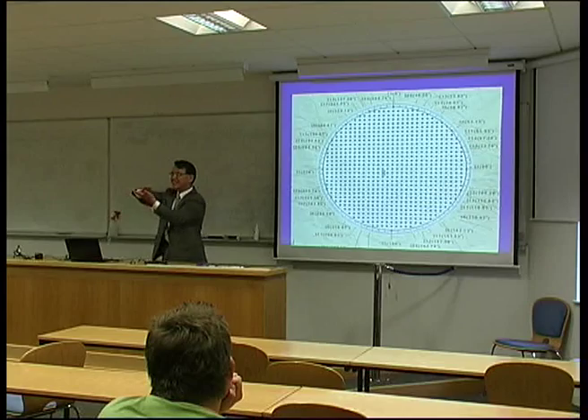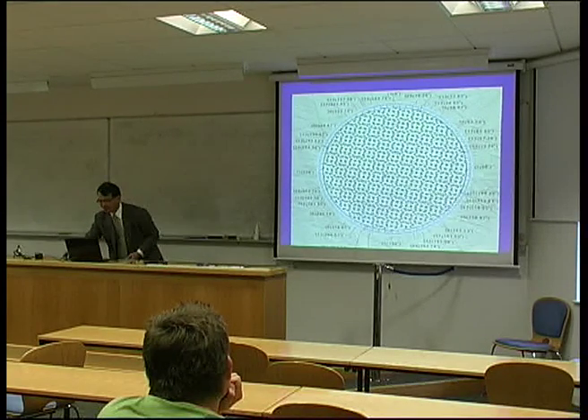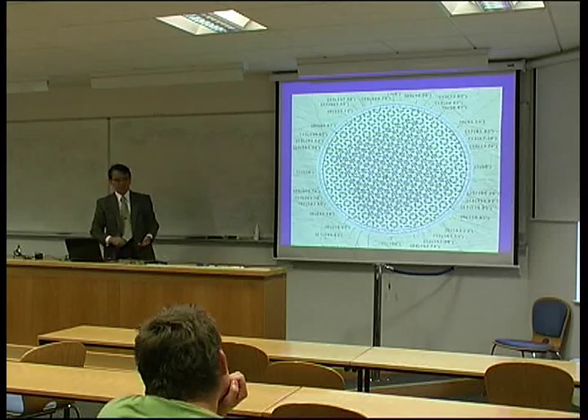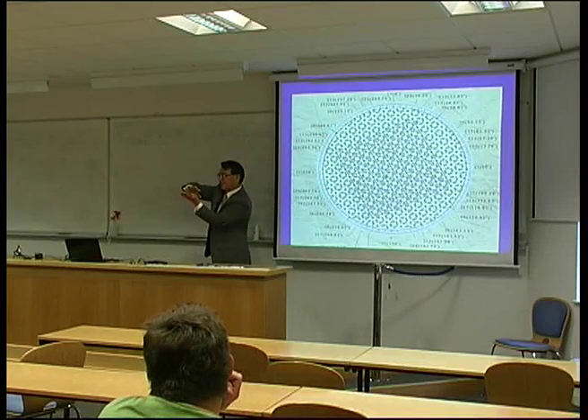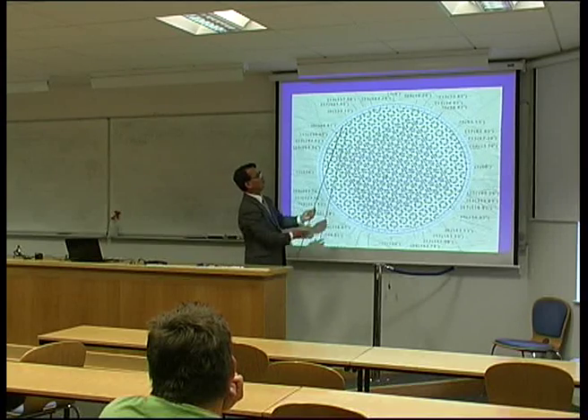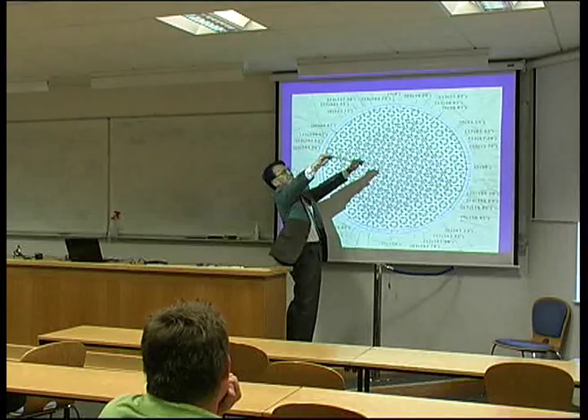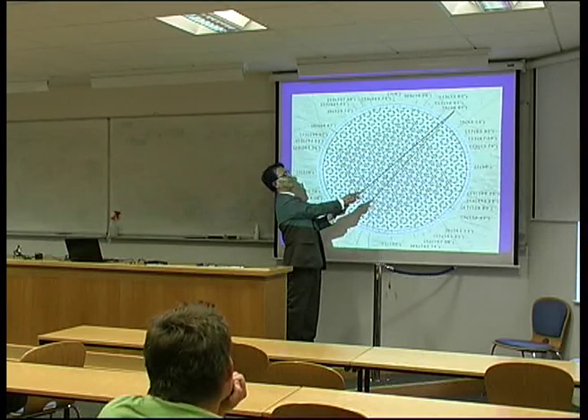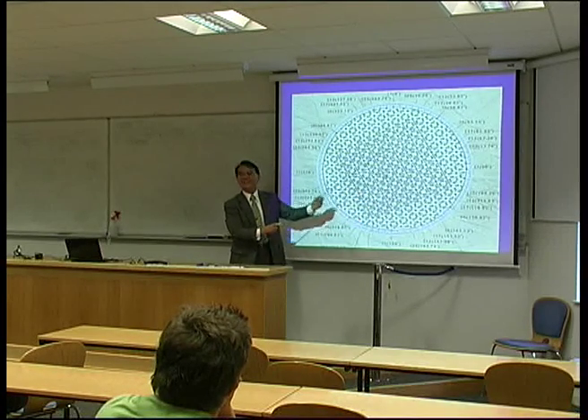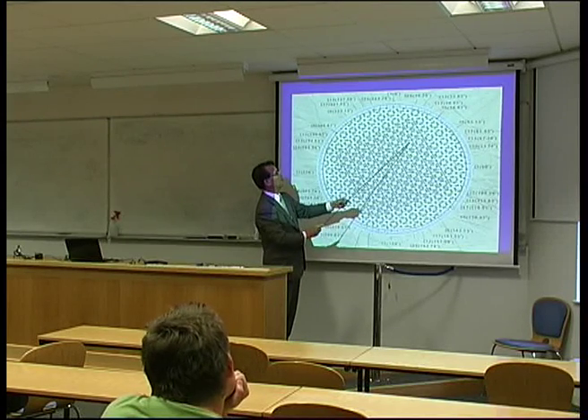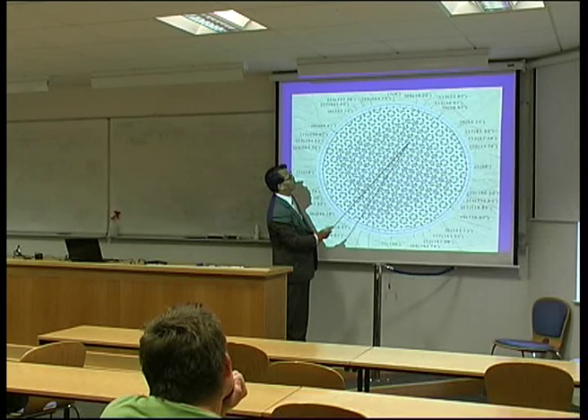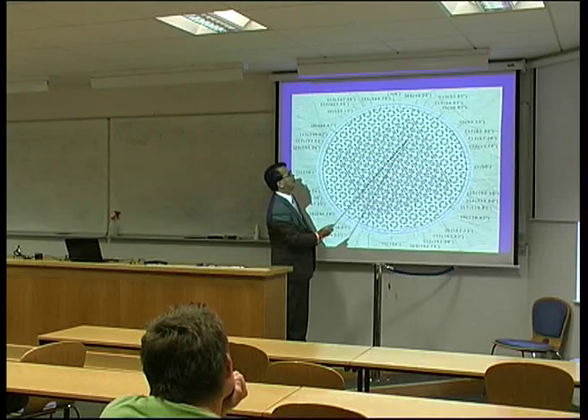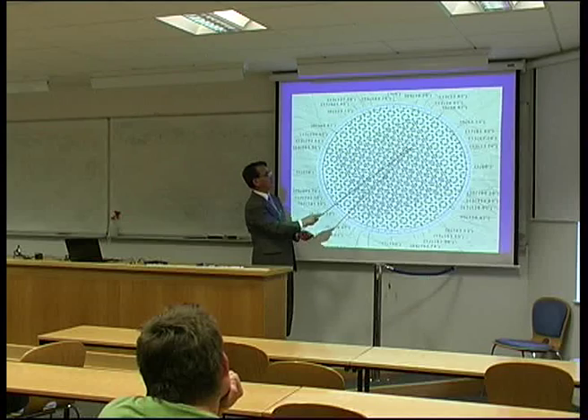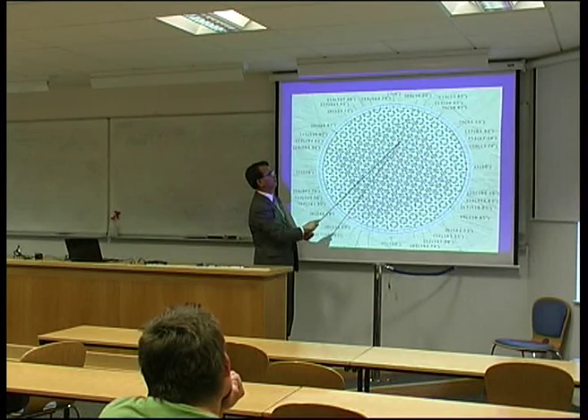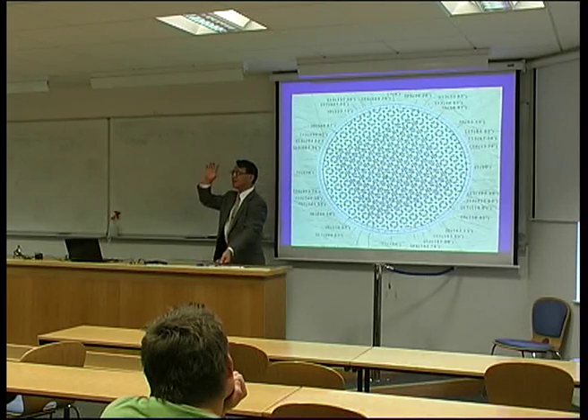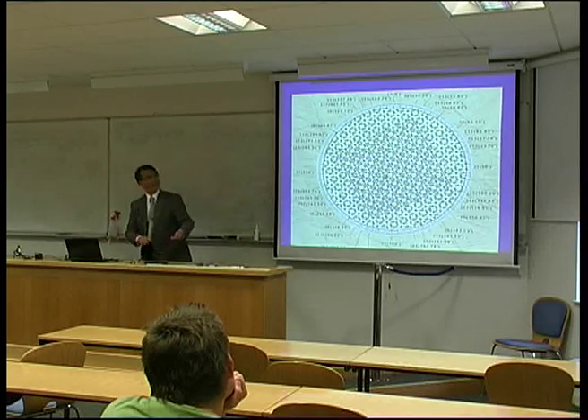But anyway, to demonstrate more clearly, let me show how to construct these lattices. Relatively rotate the two cubic crystals. So as you see, if we relatively rotate the two cubic single crystals about the 001 direction by an angle of nearly 36.87 degrees, we can construct such a superlattice. So in this unit cell, we can find 5 atoms, but on the superlattice corner, only 1 of 5 is coincident. Like this.